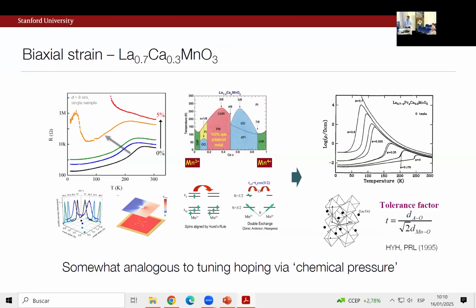And naively, we were thinking that there might be some analogy to playing games with the tolerance factor. Again, something well known to many of you in many different perovskite systems, but using the fact that we're often dealing with distorted perovskites, by changing the ionic radius on the A site, you can twist and turn the octahedra and change the electron hopping bandwidth in the system.